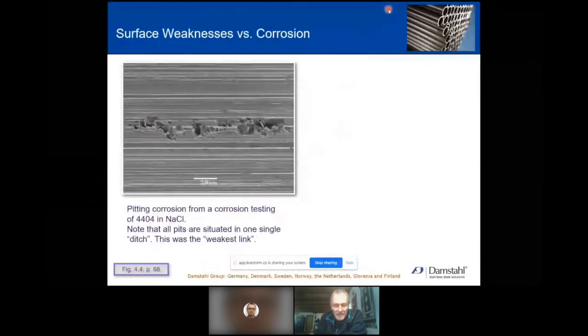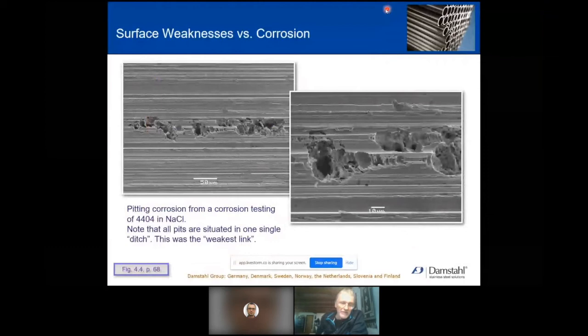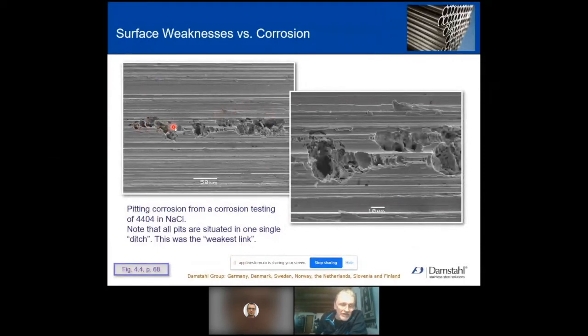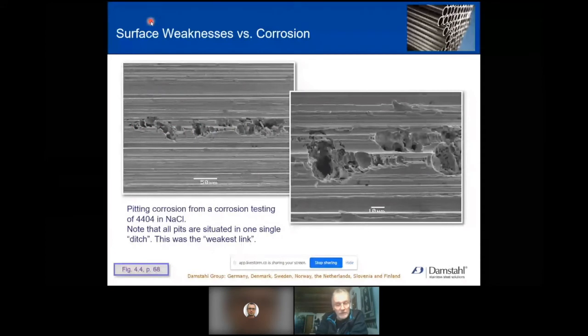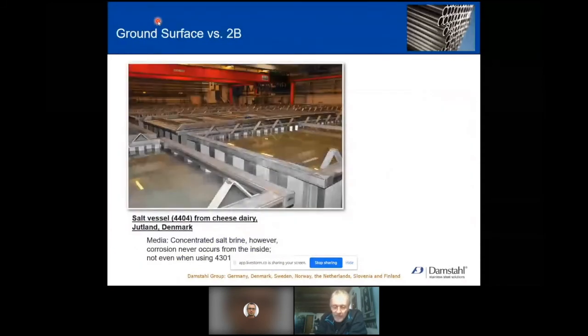This is just a very nice example of a pitting corrosion experiment where we see, especially this ditch, it has just weakened the steel beyond repair. And this is where we get the corrosion, in this case, during a corrosion test. This is a very wonderful example,